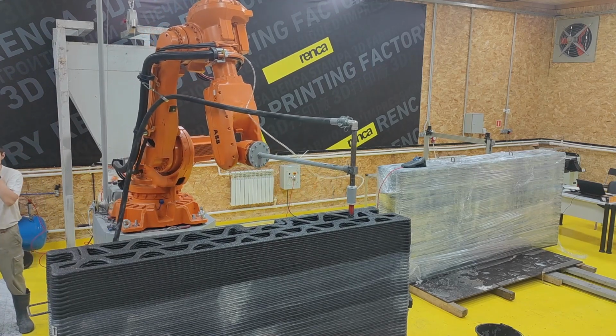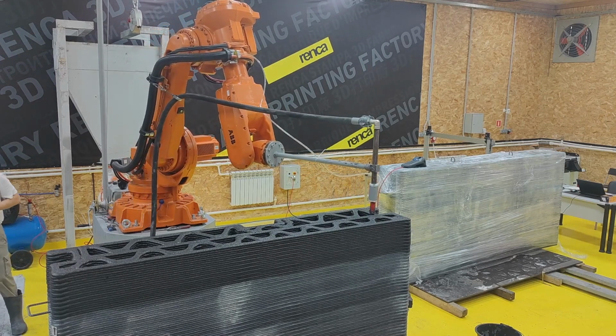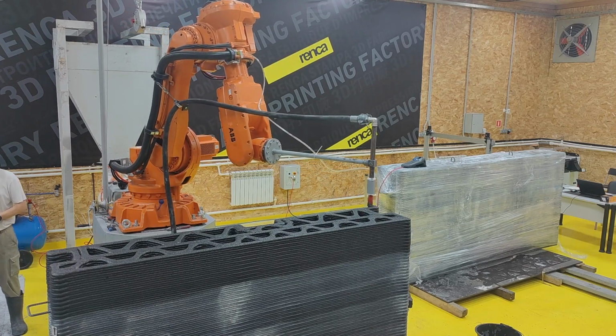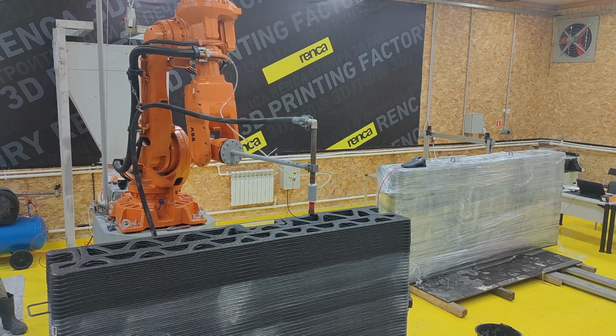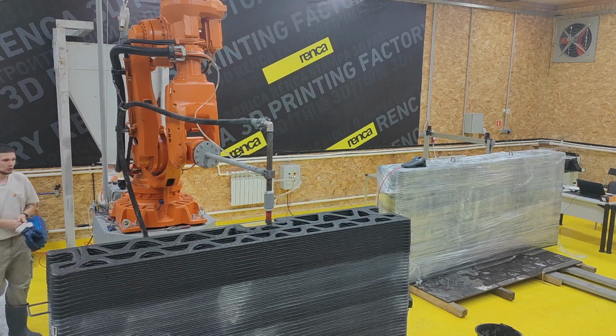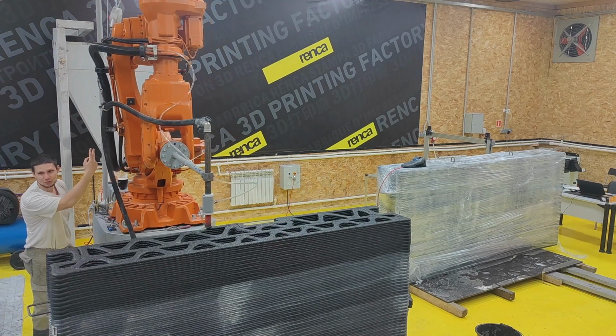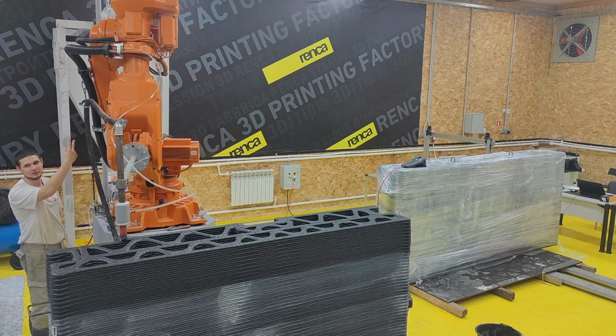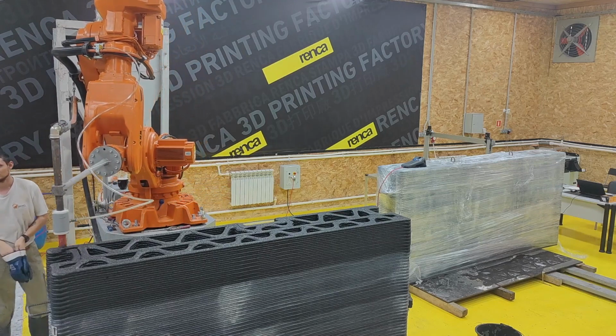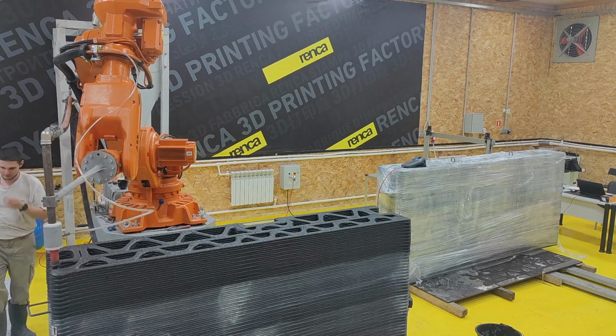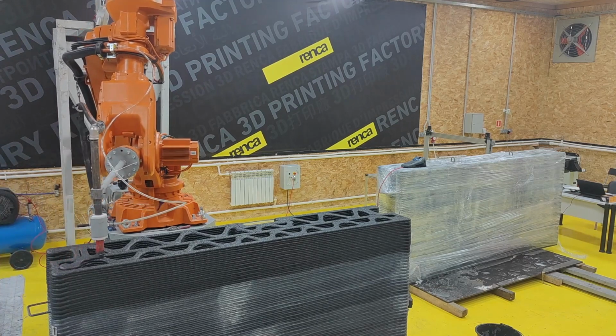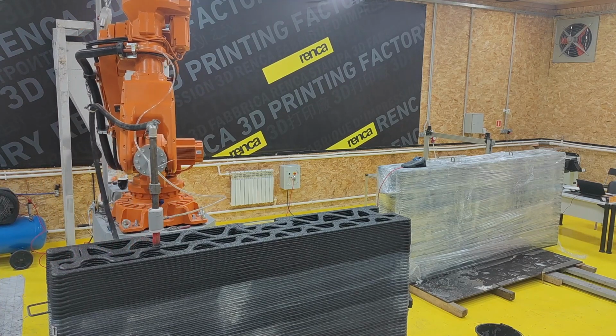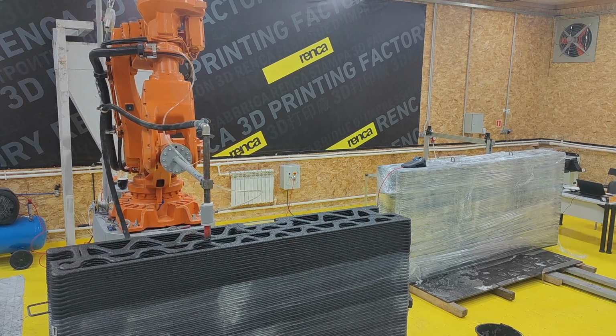In fact, in the beginning, before we started 3D printing, we tried to fight this property in geopolymer. We tried to prolong the setting time to make it more similar to ordinary concrete. But then we realized that this is a benefit, not a drawback. And we started using this feature in 3D printing. So we don't need to accelerate geopolymers. They are very fast by their nature.